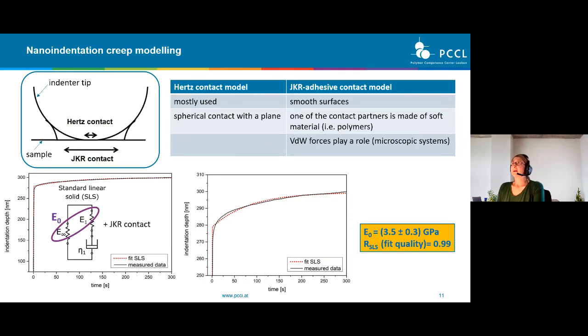Another thing is the choice of the contact model. So how is the indenter contacting the sample? The Hertz contact model, which is a spherical contact model with a plane, is the one mostly used for nanoindentation. Another model is the JKR adhesive contact model, which is used when we have smooth surfaces, or when one of the contact partners is made of a soft material like a polymer, and if van der Waals forces play a role like in a microscopic system. And here on the left, you can see that the contact area for Hertz is smaller than for the JKR model.